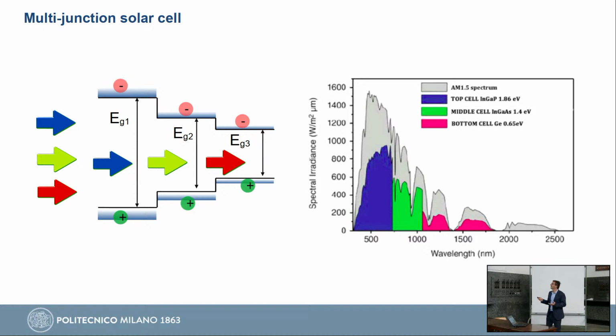and will give you the output power of a solar cell. If you compare this with the case of silicon before, again we have here the solar spectrum, and this is the part of power that I can take out from the cell, so the efficiency of the cell itself. You see that using a multi-junction approach, I can cover more and more of the visible spectrum. There is an interesting paper where you can calculate that if you make, I think, 72 heterojunctions, you will get to 94% efficiency, which is not far from the Carnot limit for a solar cell.